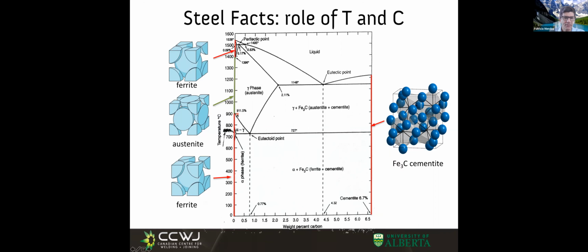Now, at 911.5 degrees C in pure iron, and more or less that for normal steels, something happens. Due to the laws of thermodynamics, at those higher temperatures, the atoms of iron say: we don't like this BCC structure, which we call ferrite, anymore. We want to arrange ourselves differently, in an FCC way. We call that phase austenite. And austenite, with that different arrangement, has properties too - among them, that it's easy to deform.